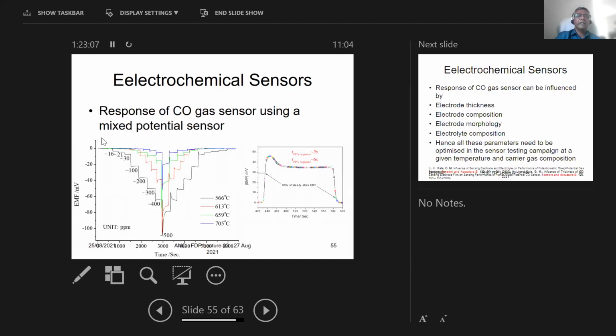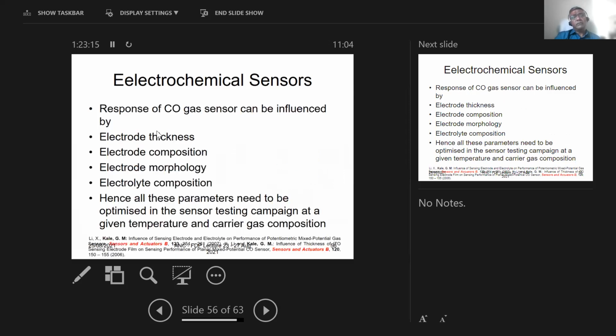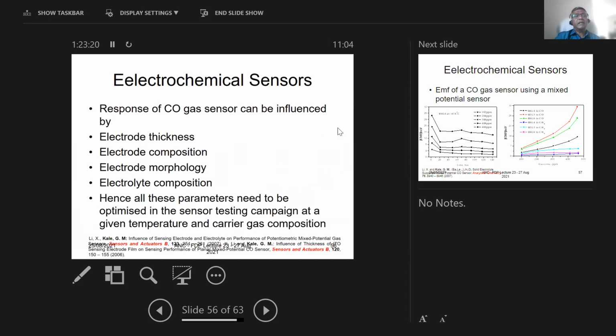So this is about the carbon monoxide sensor that we have tested. And again, similar results have been found for carbon monoxide sensors. What we have also found is that the response of the carbon monoxide sensor can be influenced by the electrode thickness, electrode composition, electrode morphology, and electrolyte composition. So we have analyzed all these 4 different parameters, and the results of the analysis were published in 2 different publications in Sensors and Actuators B from my research group.